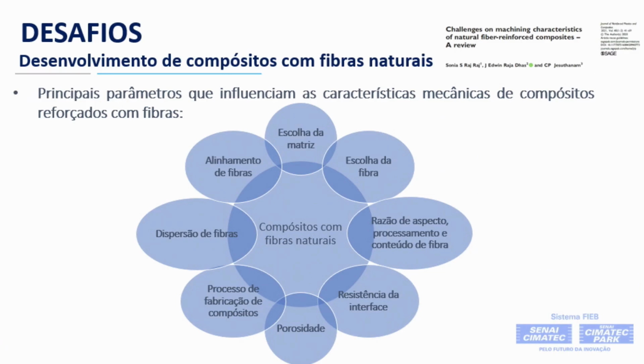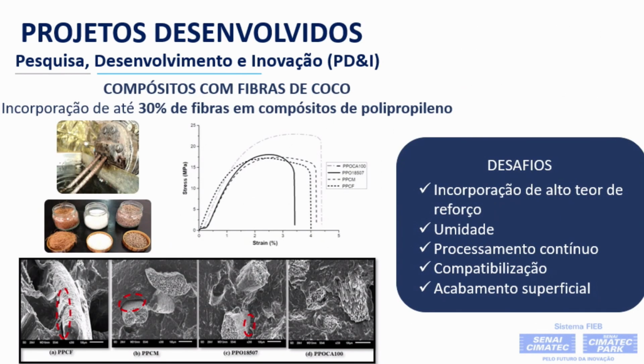We have to think about the aspect ratio, the content, the processing itself. We have to check the interface strength. If the fiber and the polymeric material do not interact well, the composite is not going to be of high quality. The fibers can vary in terms of porosity. This must be taken into account. We have to consider the manufacturing process and how to improve the dispersion of the fibers throughout the piece.